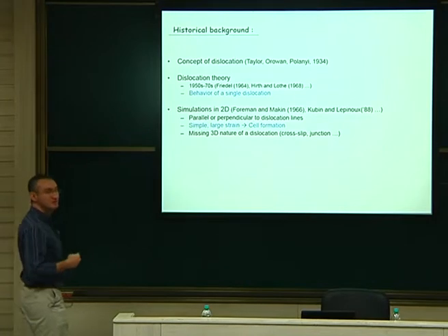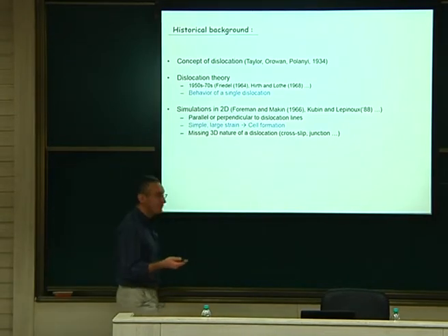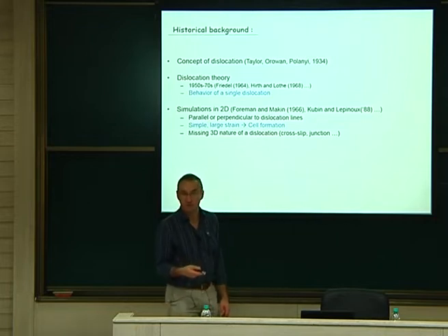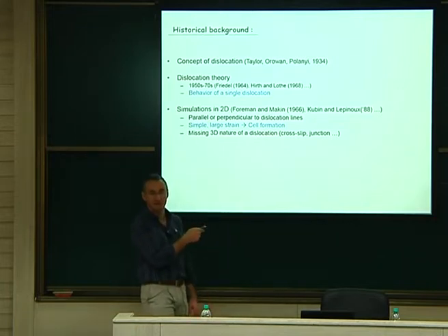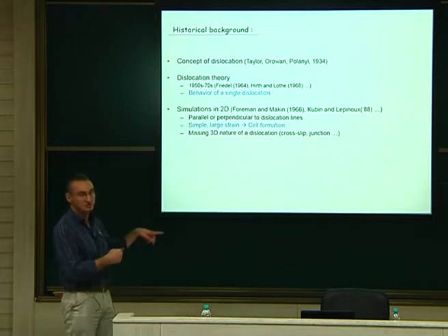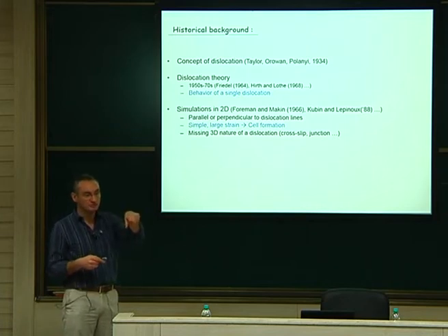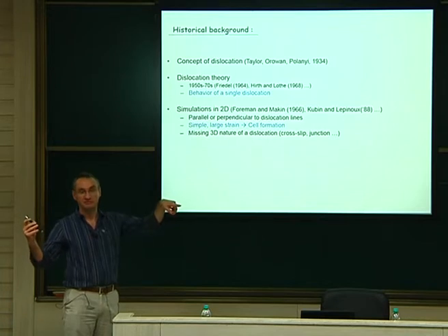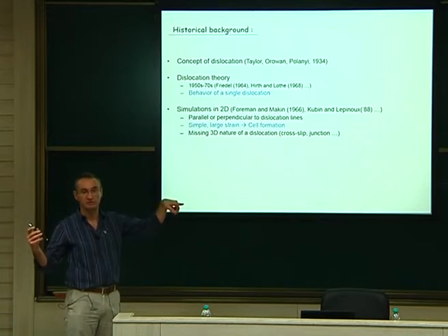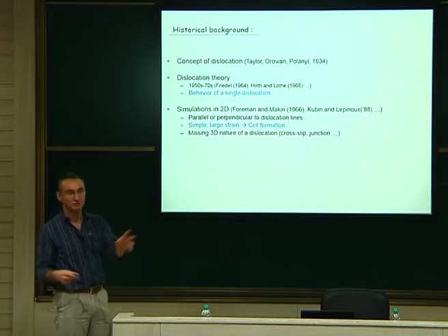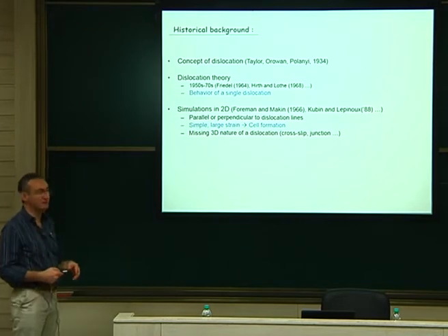This is a very simple simulation. I'm sure that now that you have the formula in the lecture I gave, you can write this in MATLAB. I think it will take one day. In one day of programming, I'm sure you are able to create your first 2D DD simulations. You just put nodes, you compute the force due to all the other dislocations, and you move them with a viscous drag velocity, and you will see your 2D simulation running. It's very, very easy. It's a code that you can do in one day, I'm sure, in MATLAB.